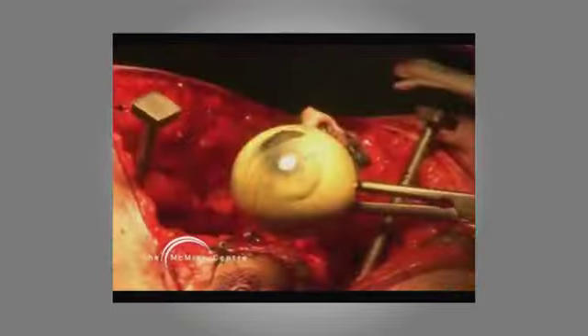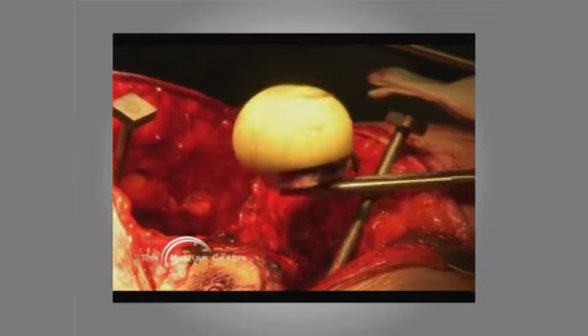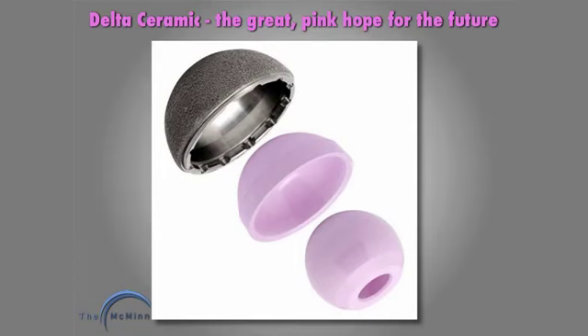We've seen in the other patients some without wear through of the metal head and just fracture and dislocation of the ceramic liner. So I put in 5, and all 5 have failed at between 2 and 3 years. Now, this was not the best ceramic ever, but Delta ceramic is a much better ceramic from a structural viewpoint. Here, metal oxides have been added to the ceramic, and the fracture rates and explosion rates of ceramic have drastically been reduced, although not totally eliminated.